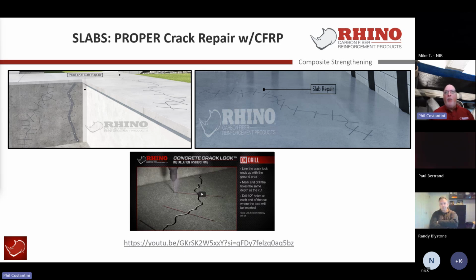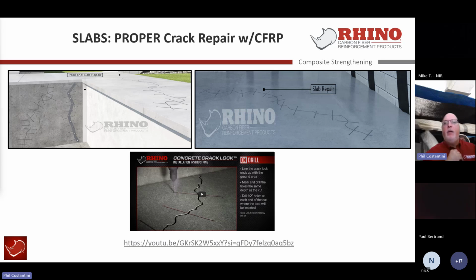The carbon fiber crack lock works very well to stabilize those cracks, so that when you put a traffic coating or a regular intumescent coating over top of it, or anything you want for a finished vehicular or pedestrian traffic scenario, it allows that crack to be stabilized and handle both shear movement and lateral movement from it opening up again. So it's a really unique application. I would focus primarily on slab repair and something that we can help design. The actual application video is available on our website on a regular basis.